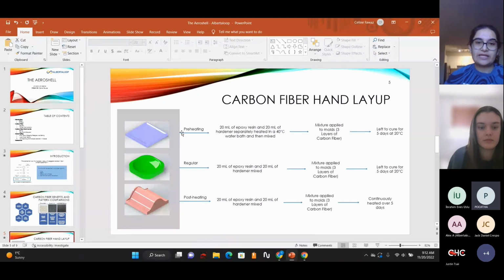So if we preheat it, which is basically like we heat the hardener and the epoxy at 40 degrees Celsius separately, and then we mix them together, and we apply very thinly to the mold and between the carbon fiber layers, which are 3 layers, and we leave that composite to cure for 5 days at 20 degrees Celsius. Whereas the regular is just the epoxy resin and the hardener mix, and you manually apply them and you leave it to cure for the same amount of time.